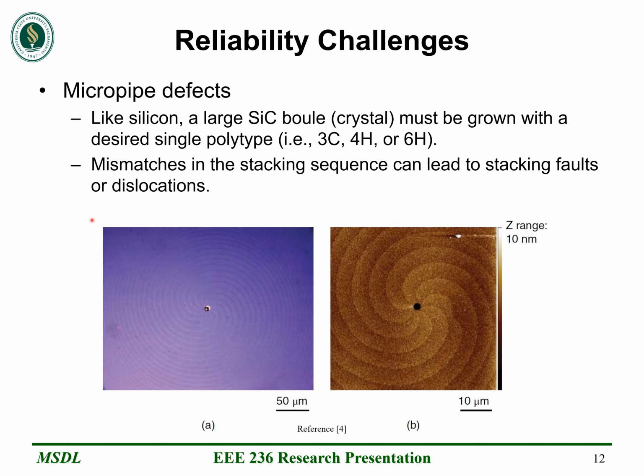Like silicon, a silicon carbide boule must be grown with a single desired polytype, whether it's 3C, 4H, or 6H. We want this crystalline boule to be as perfect as possible because we'll eventually cut it up into wafers and fabricate our microelectronics. However, mismatches in the stacking sequence can lead to stacking faults or dislocations. Down below are 2 photographs of the same stacking fault.